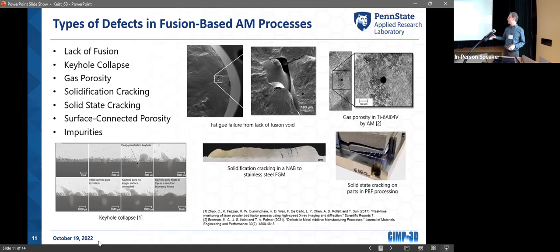So what is it? There are a lot of basic defects that we find in additive manufacturing. The main ones, the top three, start with lack of fusion. This example shows what you're doing when you're building your layer in a fusion process where you're melting. You may not have enough power, and you end up with an area that didn't fuse. And this is a failed component that had a lack of fusion defect right here.